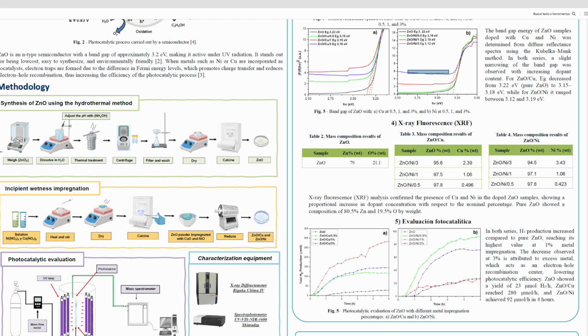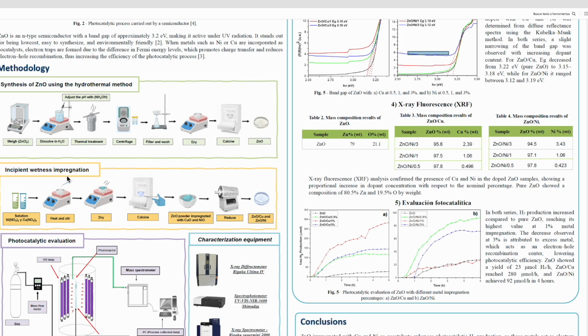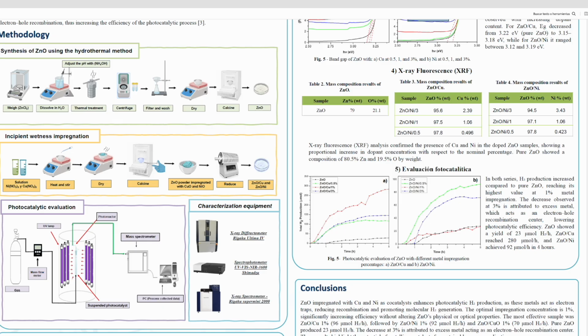So as a result, here we obtain our pure zinc oxide, but we still need to impregnate it with our transition metal. It's important to emphasize that our metal does not enter the structure of the zinc oxide. It's only deposited on the side, as could be seen in the image above. And well, once we have the zinc oxide, we prepare our metal salts with nitrate, copper nitrate, and nickel nitrate.